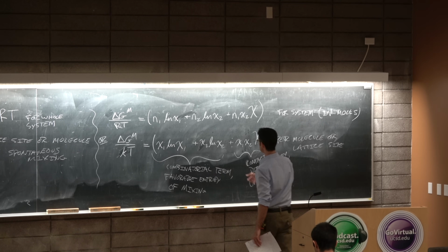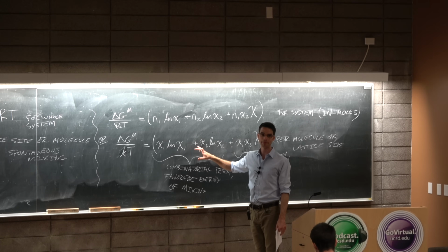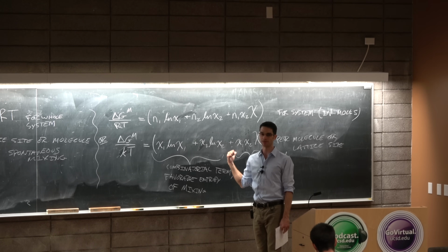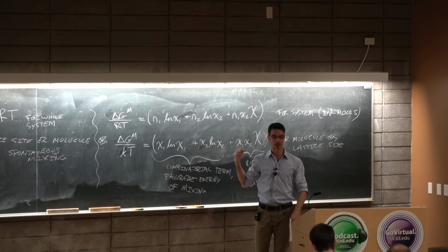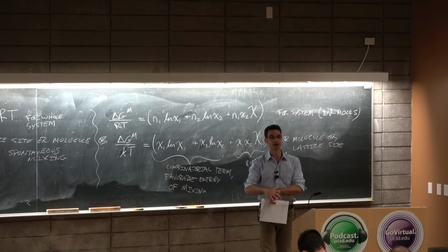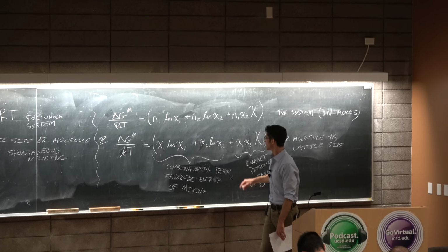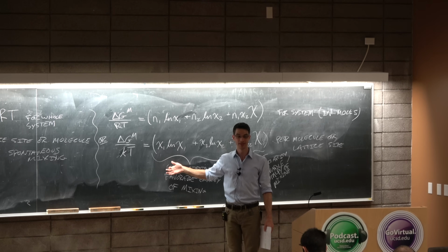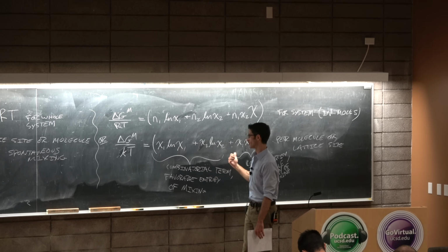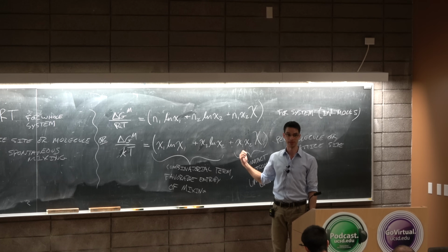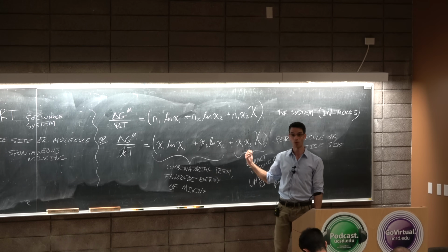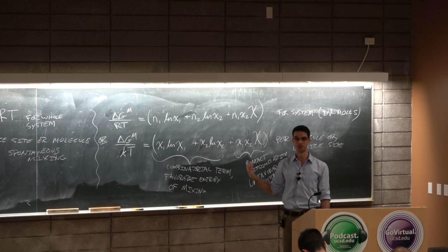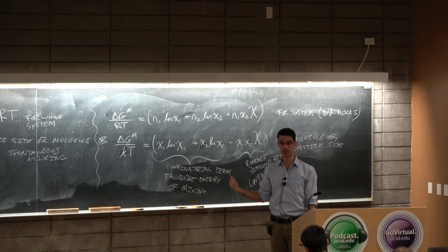And if we lose lots of this entropy, which is favorable, we're left with the unfavorable enthalpy of mixing, which encourages phase separation. Now, what if they were both polymers? Then the entropy of mixing would go to basically 0 with higher molecular weights, and the only thing we'd have left is the unfavorable enthalpy of mixing. So that's why two polymers don't want to mix together in general, although there are always exceptions.